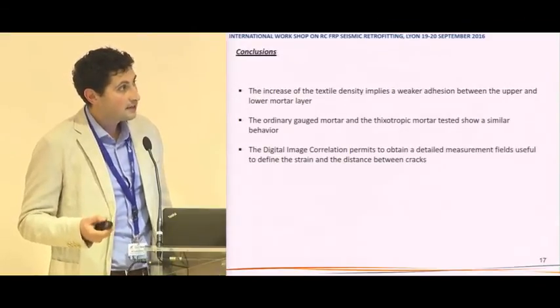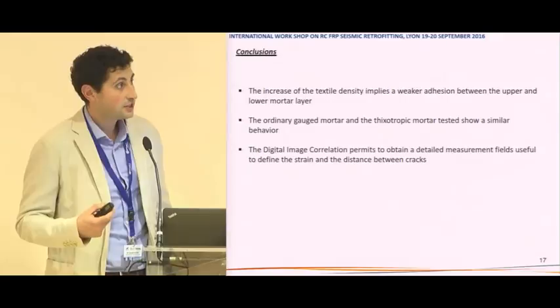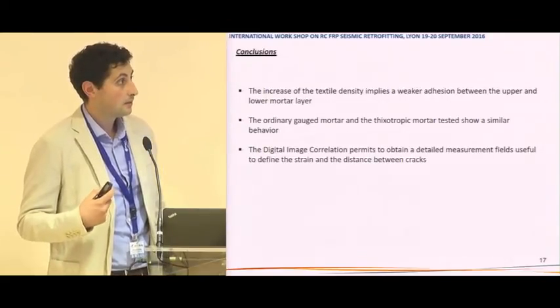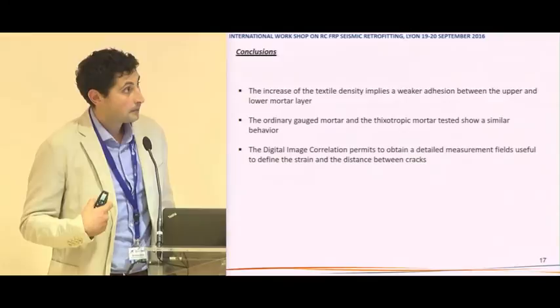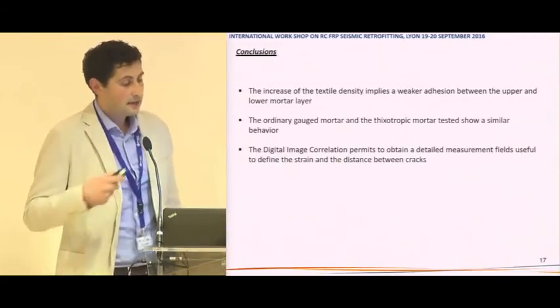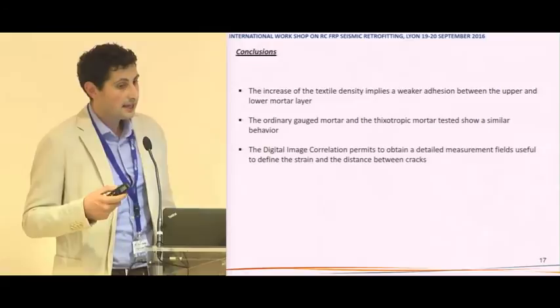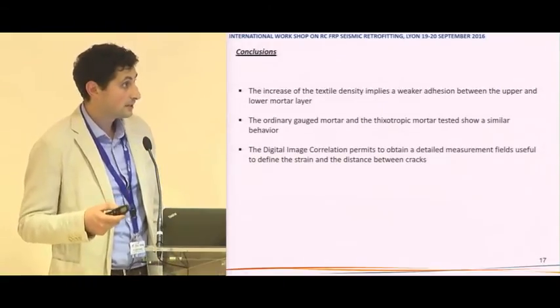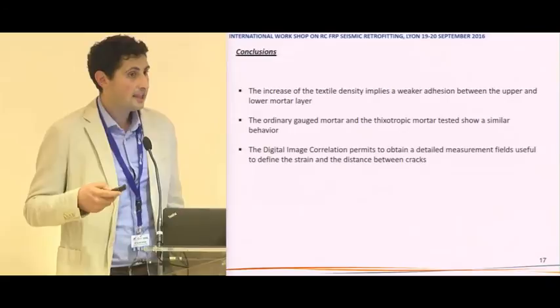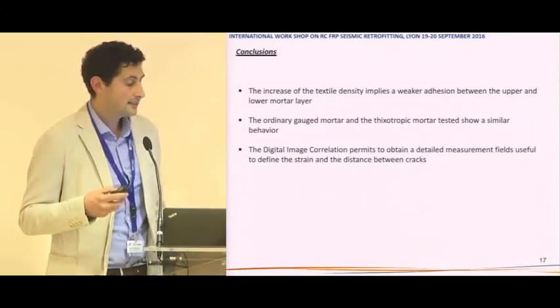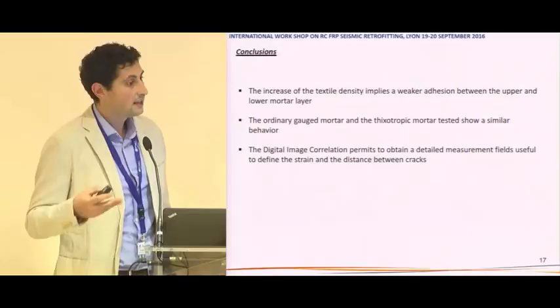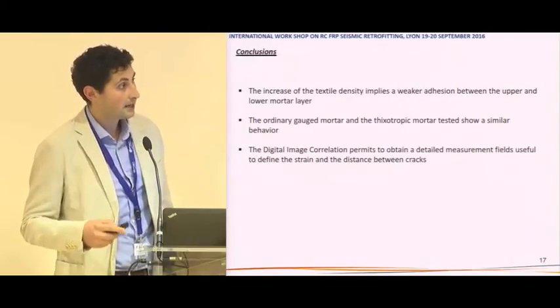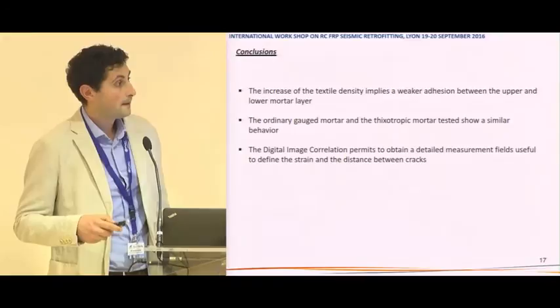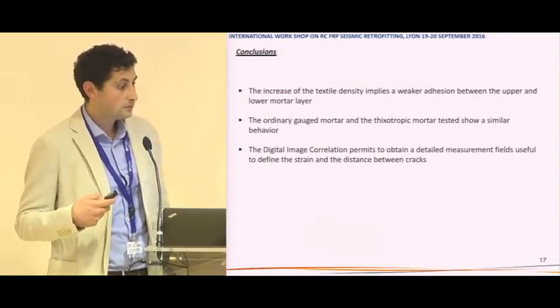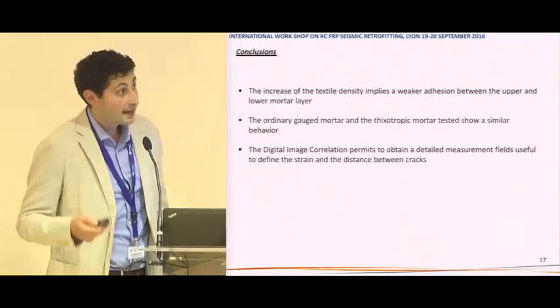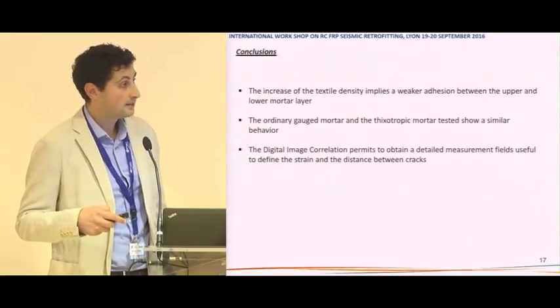Concerning the conclusion, the increase of textile density implies a weaker adhesion between the upper and the lower mortar layer. It's also interesting in our study that using an ordinary mortar, we could obtain a composite that has properties similar to a composite characterized by thixotropic mortar. Digital image correlation could be a useful tool to characterize this kind of material too.